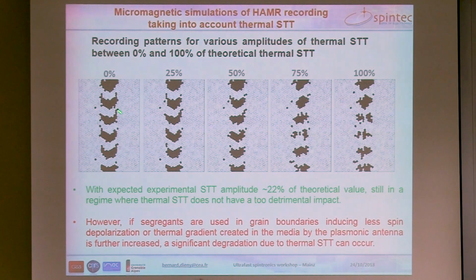What you see here is without any thermal spin transfer torque in the media, so neglecting this effect. We see that with 25%, the transitions are not yet much perturbed. So the effect is still not very important. But if we go to 50%, we see already a degradation of the bits. If we go to 75%, the degradation is much more pronounced. And at 100%, the degradation is really very strong.